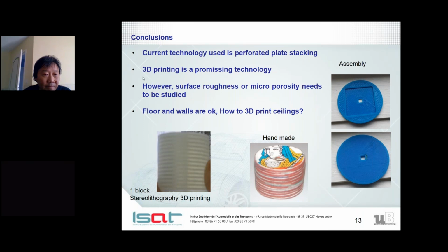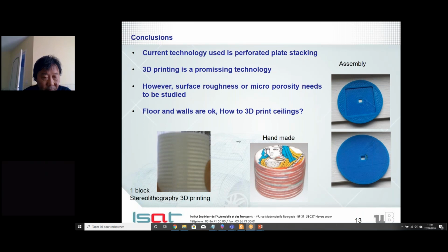Okay, so I believe that I can ask. Philippe, because you said that they 3D printed this sample using resin-based stereolithography. And a comment to this is that when you use different technologies, you must be very careful, because some of them require treatment. For example, when you use stereolithography, you don't have problems with microporosity, but you may have problems with the resin. And you need to get the resin out of these, let's say, small slits, for example, in your cake, between the pancakes. And there's also a problem with curing using ultraviolet light. So this can be very problematic.